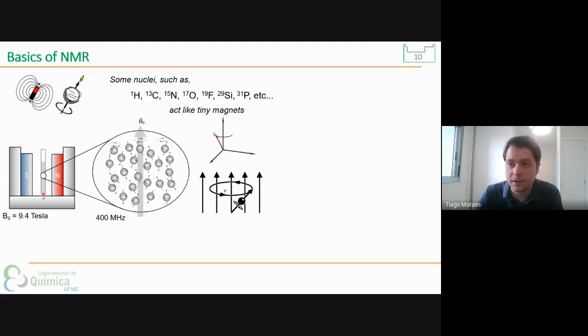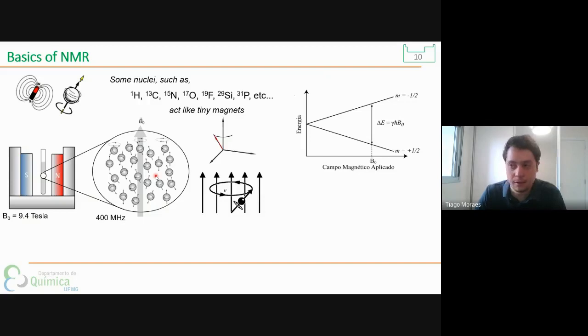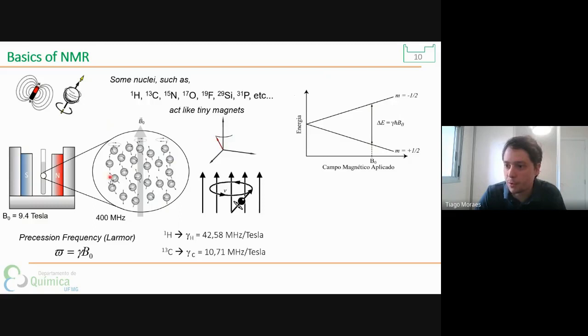When we insert our sample in an external magnetic field, like for example, 9.4 Tesla, the nuclear spin will precess, will do this movement, as you can see here, and will be separated, for spin 1/2, in two energy levels, as you can see. And in this spectroscopy, we want to see these energy levels. So the nuclear spin, for example, of hydrogen will precess with a precession frequency that depends on the nuclei because of the constant here. And for hydrogen it is 4 times the precession frequency of the carbon in the same magnetic field, as you can see.